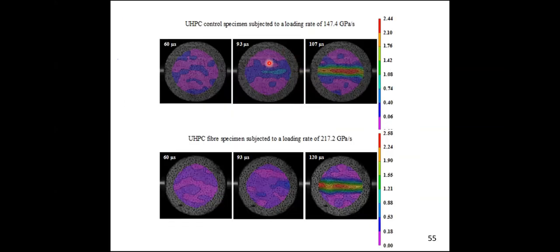Again, with the help of DIC, the digital image correlation, from the strain contour plot, we can see the crack initiation. You all know when the material is being loaded, the material will fail through crack growth, and then it will lead to final fracture. We cannot see the fine crack using the naked eye. But with the help of this DIC, you can see the crack initiation. At 93 microseconds, a crack started generating. At 107 microseconds, you can see a big crack.